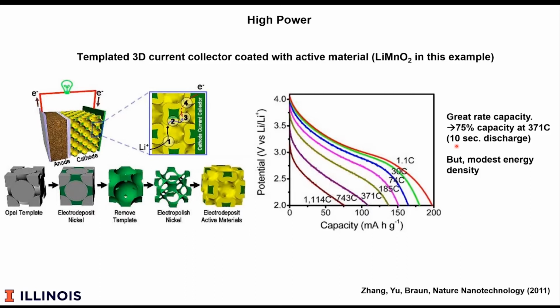We could also charge this cathode. So remember, the cathode isn't really where the charging problem is, but we could charge the cathode quite rapidly also. But the problem was that the active material, the energy density, the amount of material in yellow was only about 40% by volume. So while that may have been competitive 10 or 15 years ago, in today's batteries, the active material makes up something like 70 to 80% of the volume. And if we try to put that much into the system, all of the little holes you see here fill up, and we lose the rate capacity.